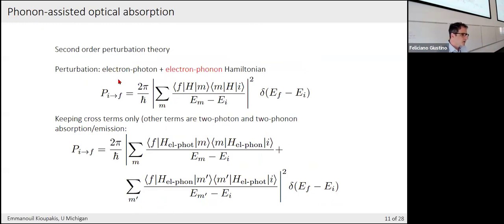and evaluate the combined effect of coupling to photons and phonons. Going back to Fermi's golden rule and going to second order, we see again 2 pi over h bar, a delta function to conserve energy. And now our matrix element is different to account for the fact that the Hamiltonian is going to second order. It involves this sum over intermediate states M and this energy denominator so that the units match as well.